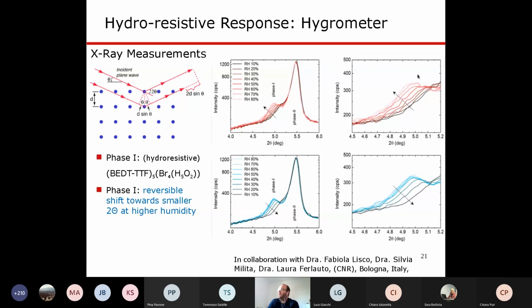And in fact, this one over here is just a zoom out of this first region over here. And we can see that this peak slightly shifts to lower values and then slightly comes back to the same position as before. And this full reversibility we attribute to this humidity response. The second peak, as you can see, is not responsive to change of humidity. So there is no change going on. Now, as I mentioned before, we could actually try, or we did calculate this distance, right?